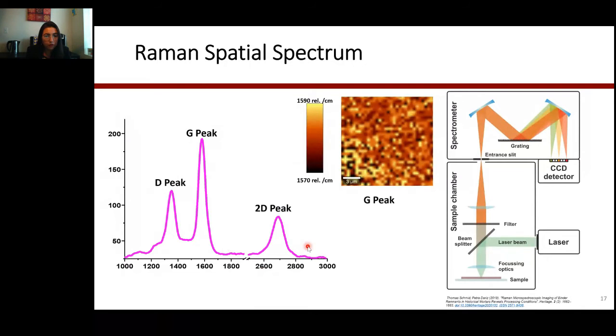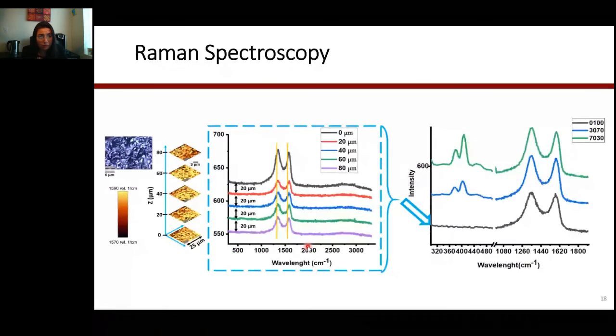So this is done for graphene, and in our case, I had MoS2 and graphene oxide because I did lyophilization, the freeze-drying. I also used an oven for oxidizing, so I had reduced graphene oxide, and after the reduction, we don't have that third peak that you showed before. So as you can see here, mostly the peaks of MoS2, and in this case, the peaks of MoS2 and graphene oxide.